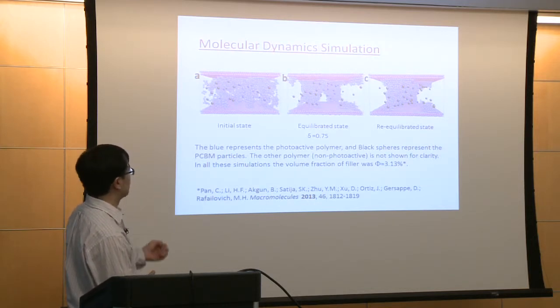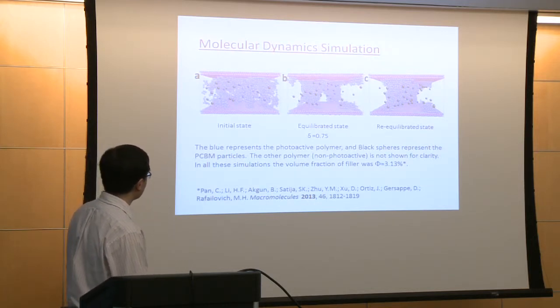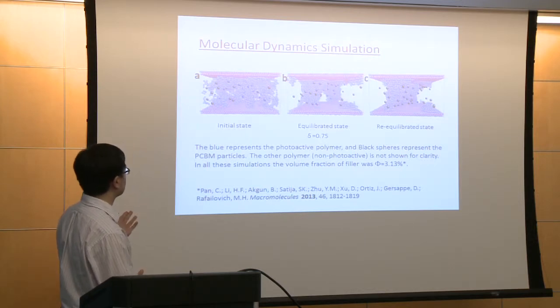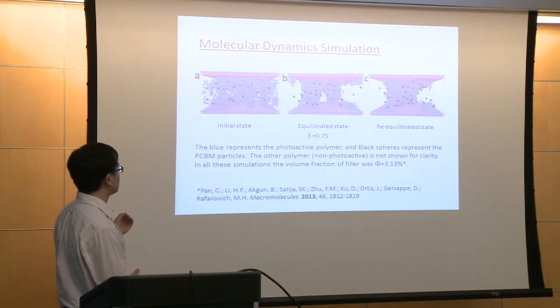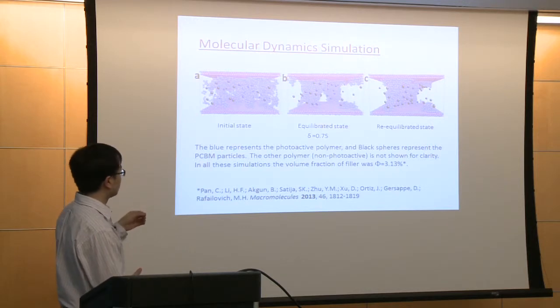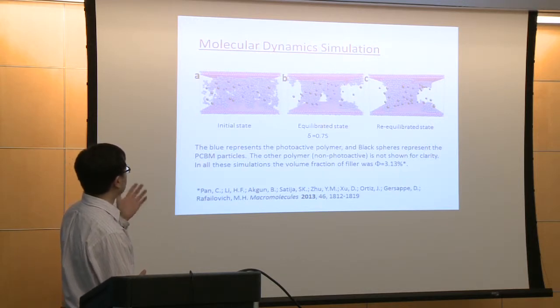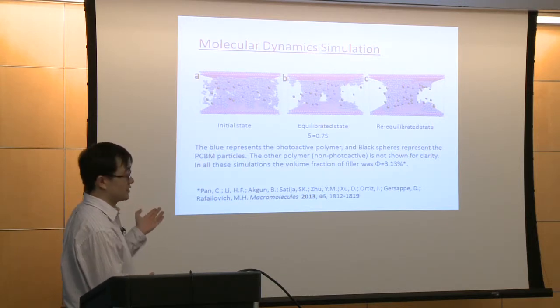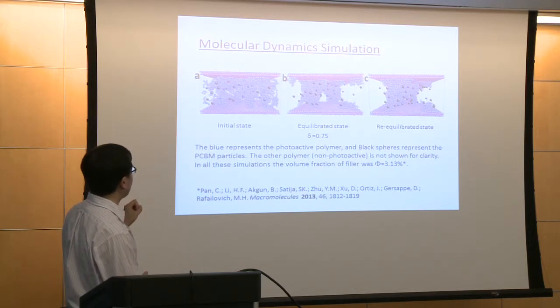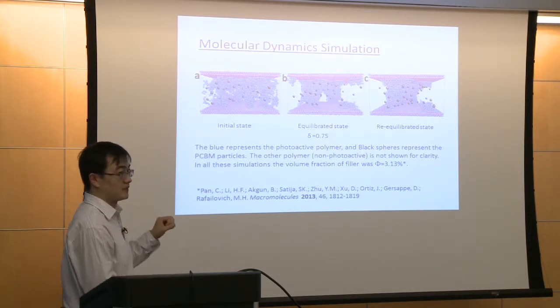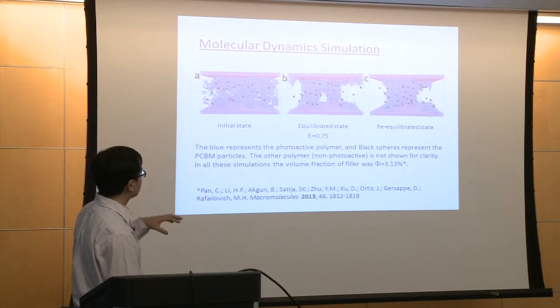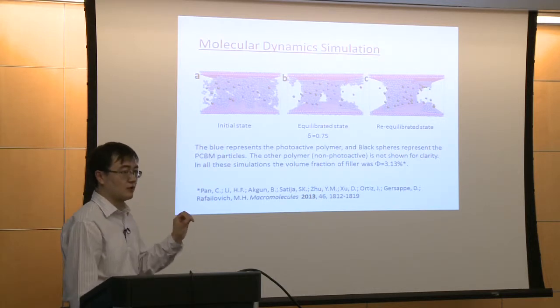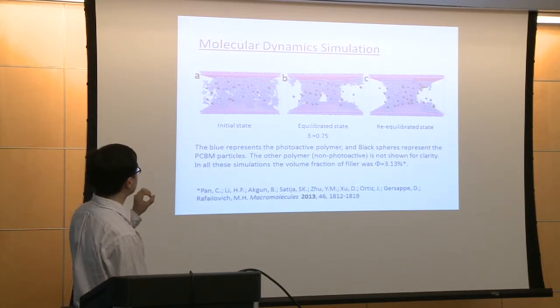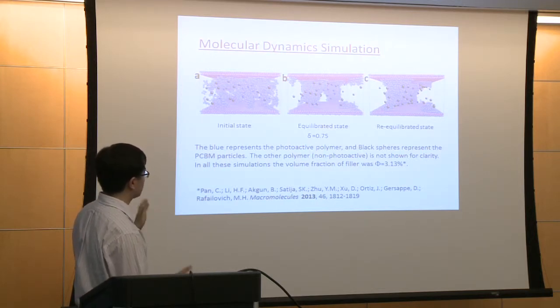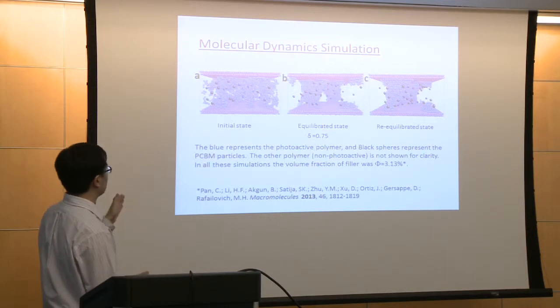So here you can see 3 states of the system. The first one is the initial state. So it's just a P3HT and a PCBM and a secondary polymer. The blue part is the P3HT phase, and the black spheres are PCBM nanoparticles. And the secondary polymer is not shown just for clarity. Okay, so at the initial state, you can see they are just mixed together.